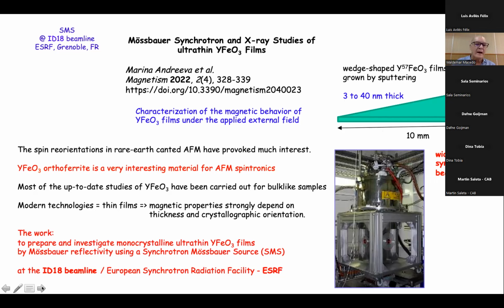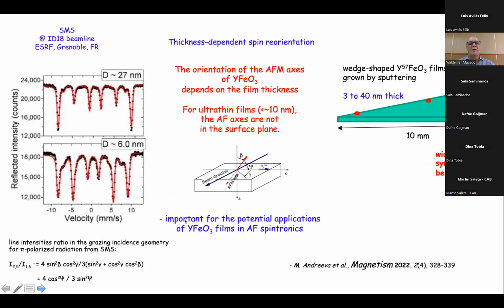And what they got is this. We see that for a film that is only 6 nanometers thick, you see this kind of spectrum. If you measure at another point some millimeters away, with a larger thickness, for example this point and this point, and you compare both, you see that the line intensity ratio is totally different. That means what you are seeing is a depth or thickness dependent spin orientation in the material. That means the orientation of the antiferromagnetic axis of this orthoferrite depends on the film thickness.